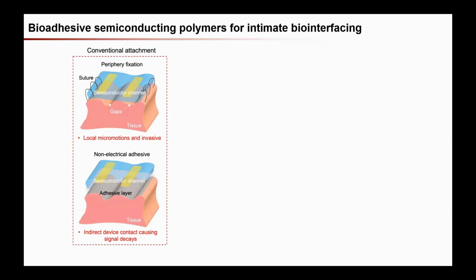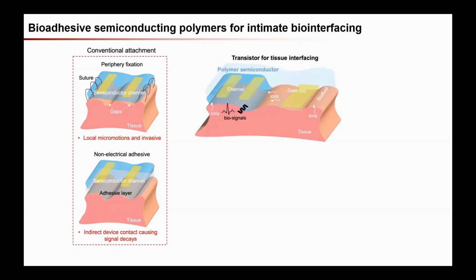And another possible approach is to add adhesive there that is not electronically conductive at this interface. So the disadvantage is it further pushes the device away from the tissue surface and increases the interfacial impedance. And for these two strategies, it is particularly not so compatible with OECTs for tissue interfacing, because as I've shown earlier, the part that really gives the sensing function is a semiconducting channel. You need to have the channel to be able to receive the signal.